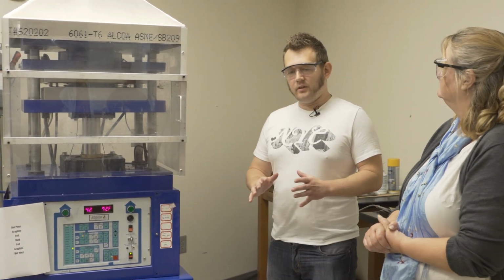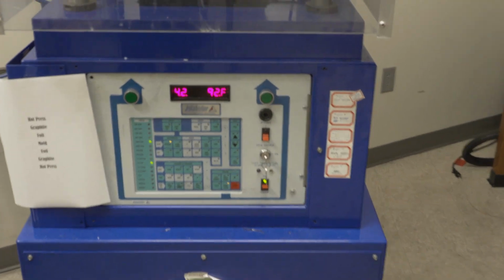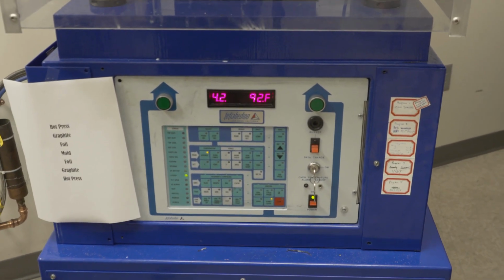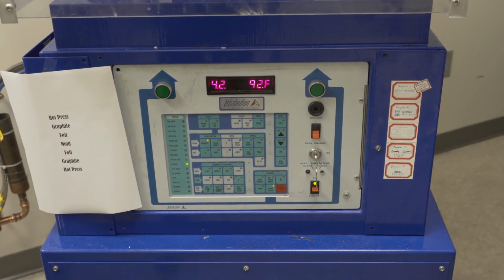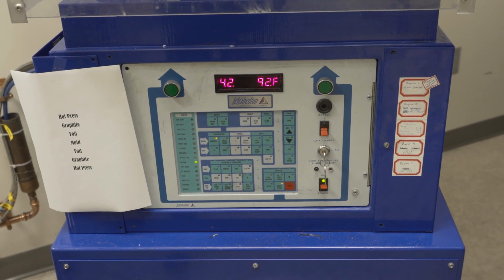And how long does the sealing phase take, and how long does the heating phase take? The sealing phase takes just 30 seconds. Then the heating, we're going to heat to 550, and we're heating at a rate of 3 degrees per minute. So it's going to take 2.5, 3 hours to do that.